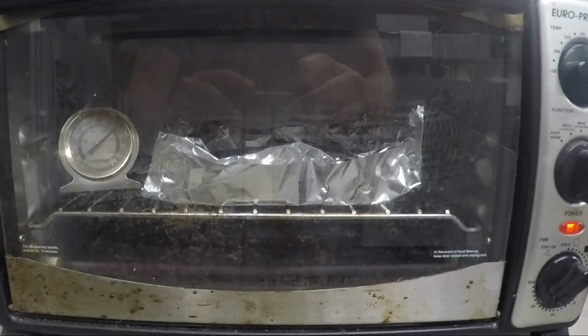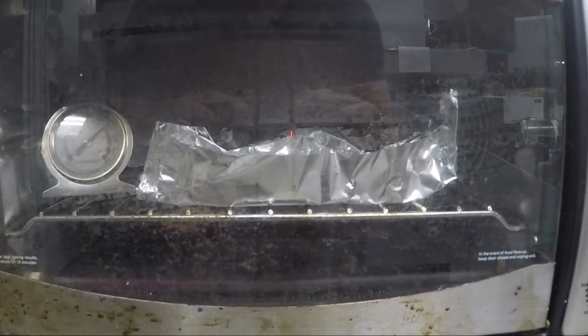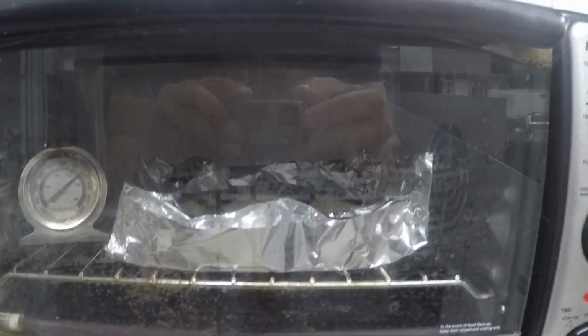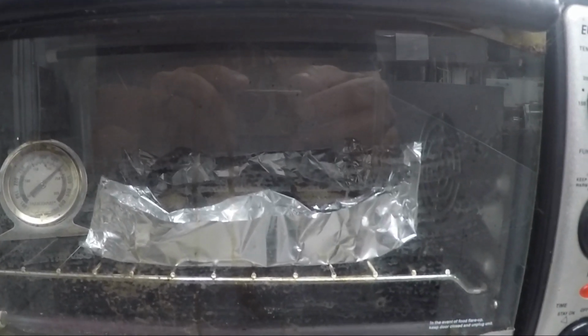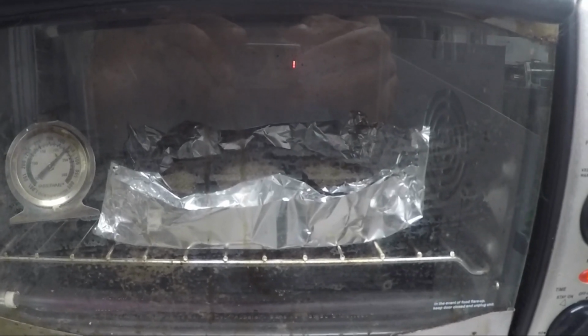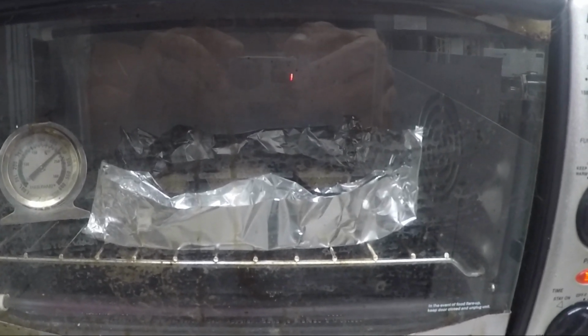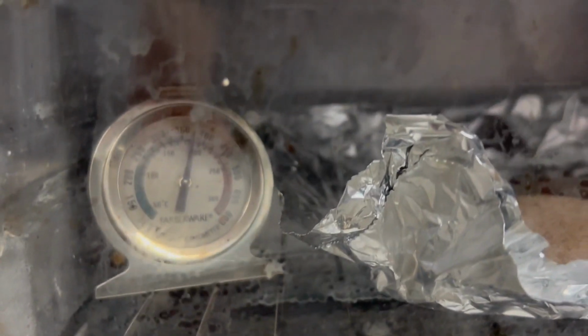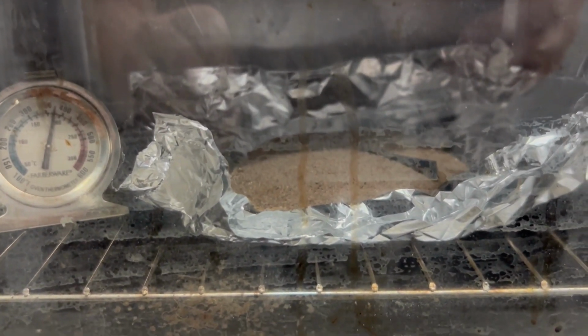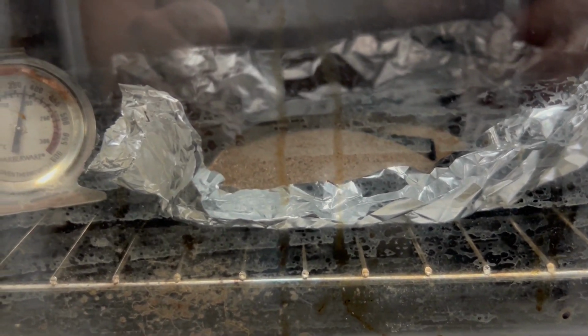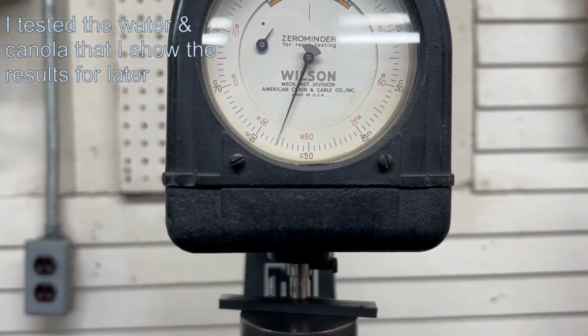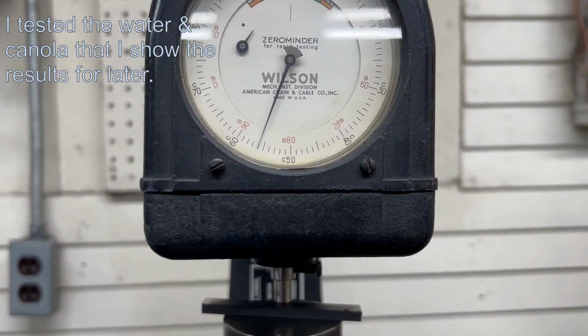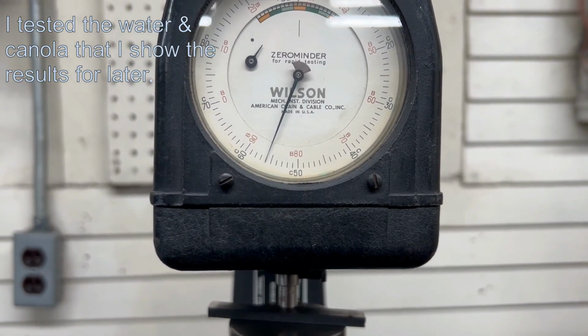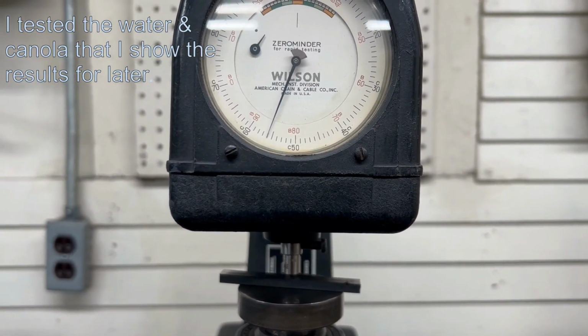Doing 3 sets of tempering at 450 degrees, 1 hour apiece, on the water quenched and the canola oil quenched. Then we're going to test the Rockwell hardness after those are done in the tempering furnace. 375 tempering for the Parks 50 quench. You see there we got 375, and we'll give that one a good temper for 1 hour. Parks 50 after tempering at 375 in the toaster oven, I got a Rockwell of about 56. So that would be our end result on the Parks 50.